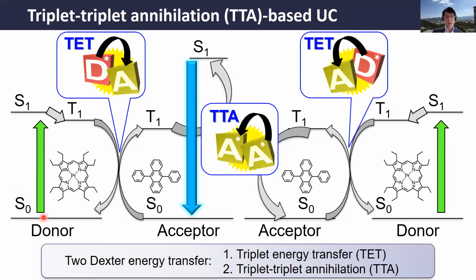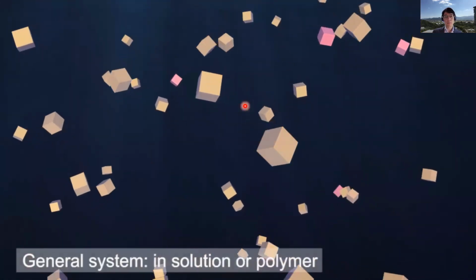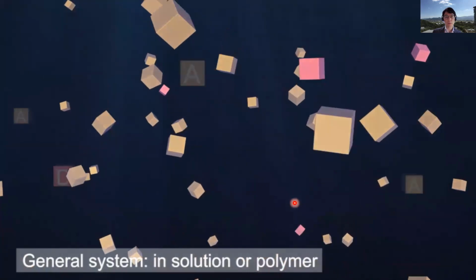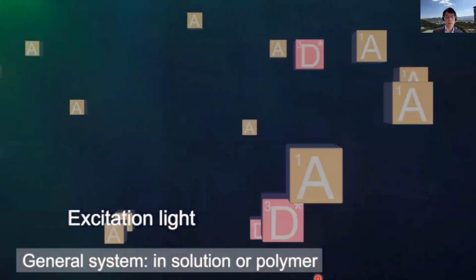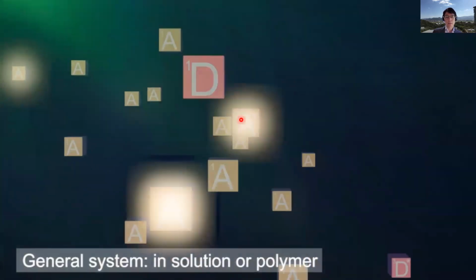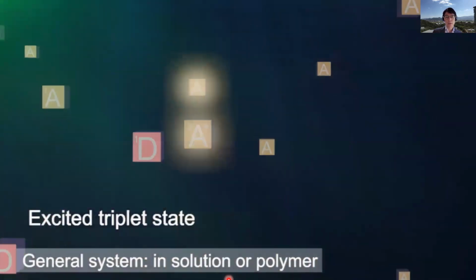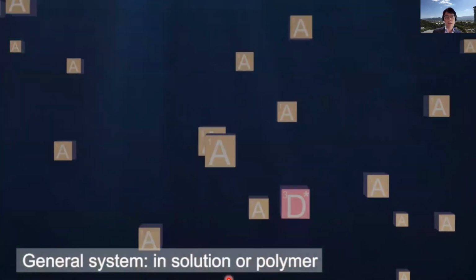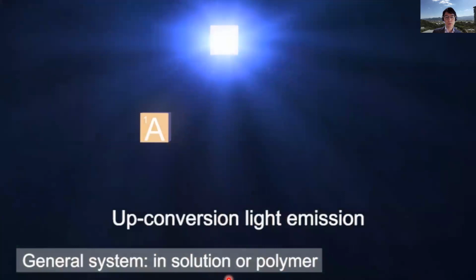So basically you absorb two photons to emit one high energy photon. To do that, you need two triplet energy transfers, and also one inter-acceptor TTA. To achieve these three events during the lifetime, people usually use molecular diffusion in solution or soft polymer. So you have a soup of donor and acceptor, and you shine the light, and the donor transfers the energy to the acceptor, you populate acceptor triplets, and then these acceptor triplets finally meet to show upconversion.